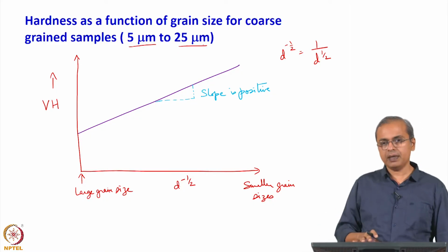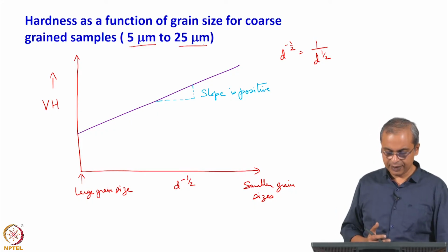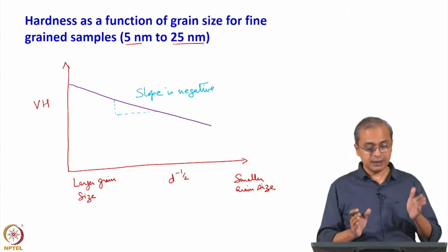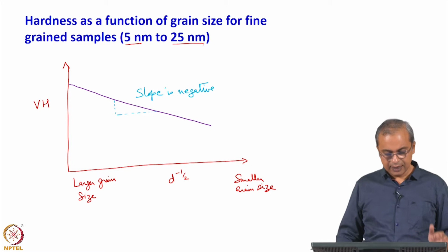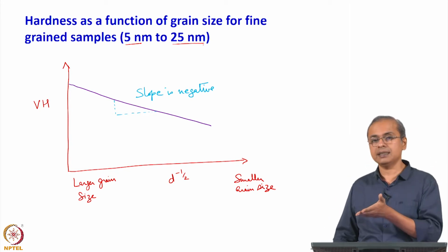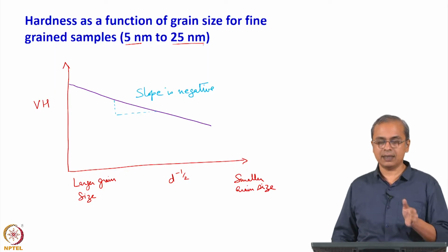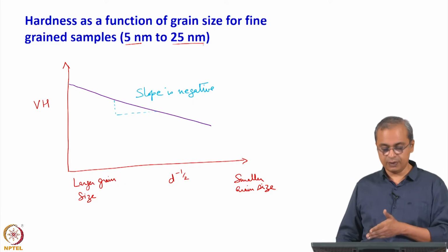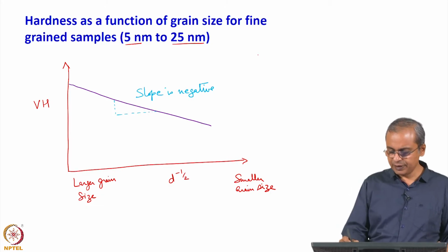Now, the same phenomenon, when you study it for nano grain sized materials, we find the opposite, the slope is negative. Therefore, it means that when you are in this 5 nanometer to 25 nanometer size scale, then when you go from about 25 nanometers to 5 nanometers, so you are reducing the grain size, which means you are going again from left to right on the x axis, the strength is actually coming down, right. So, the slope is negative. So, this is referred to as the inverse Hall Petch behavior.